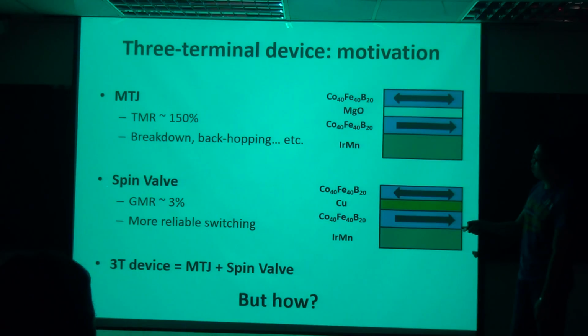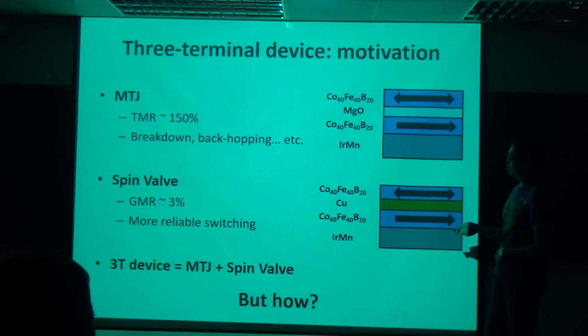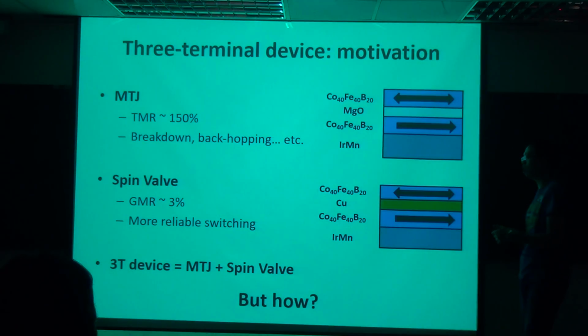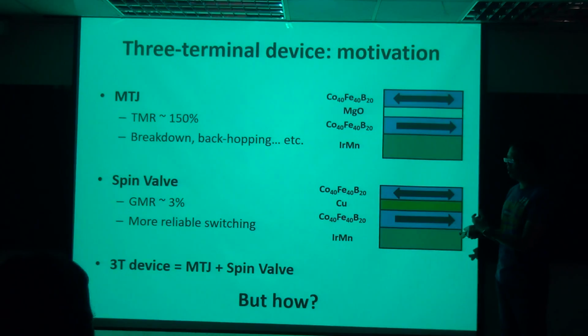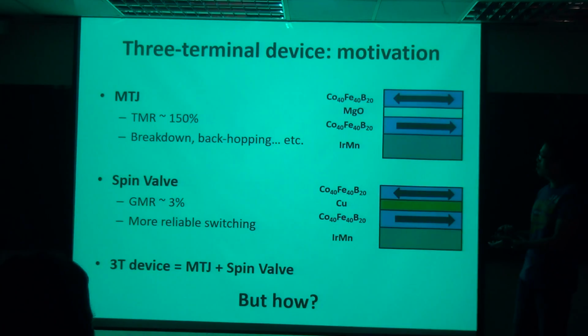And the spin valve, which is the all-metallic structure, the good thing is it has more reliable switching. So you can apply large voltage, large current, and because they're all metallic, we don't have to worry that much about breakdown. But the GMR, the MR ratio, is only 3%.